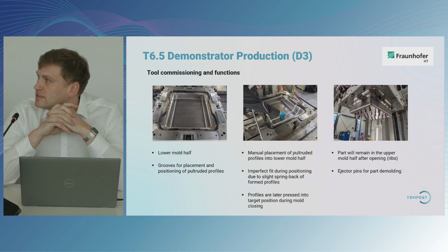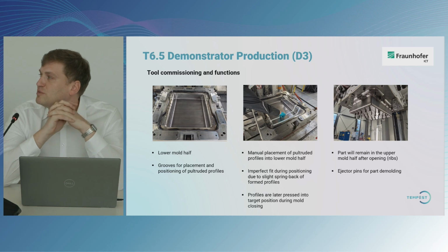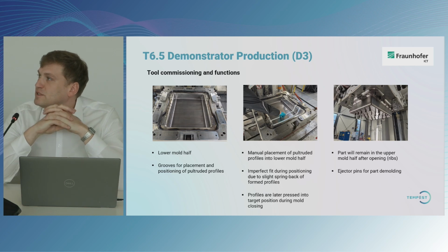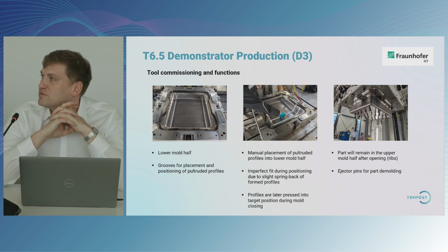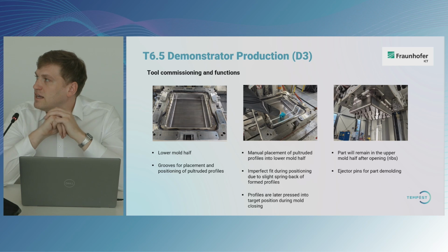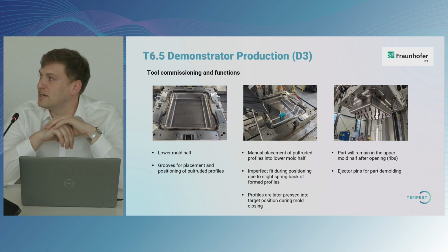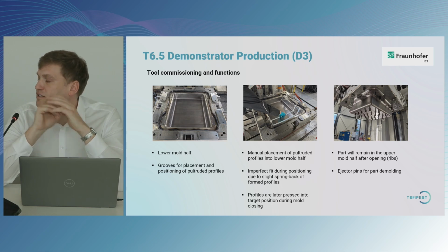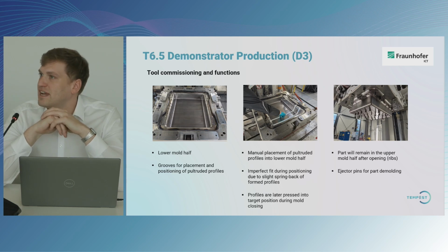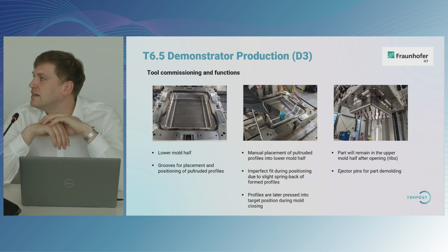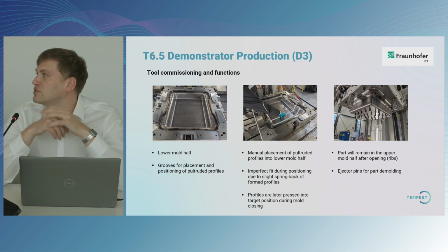So we have a mold consisting of two halves, a lower mold and an upper mold. In the lower mold shown on the left, we have grooves that are used to place the profiles mentioned before. So we place them manually, and even though they are maybe not 100% perfect in the geometry because they have a slight spring back, during the process everything is put into position, and this works really well.